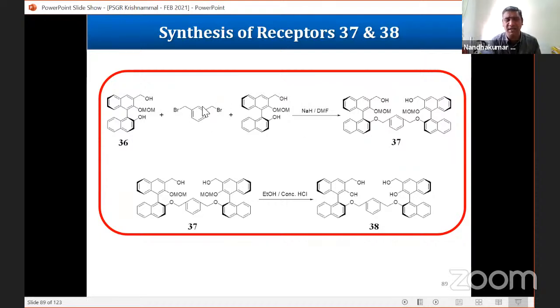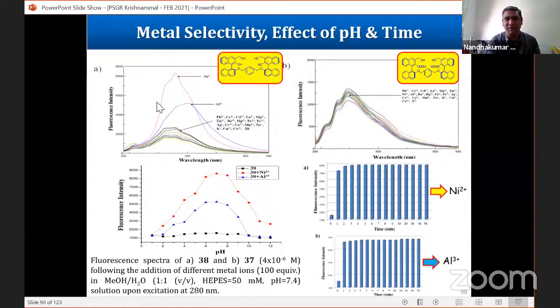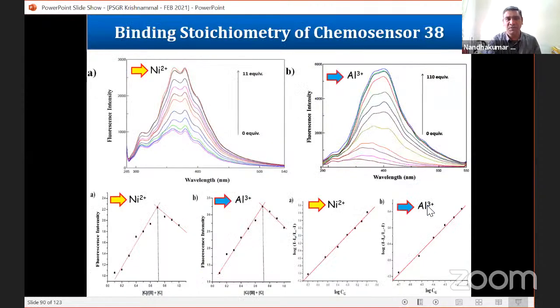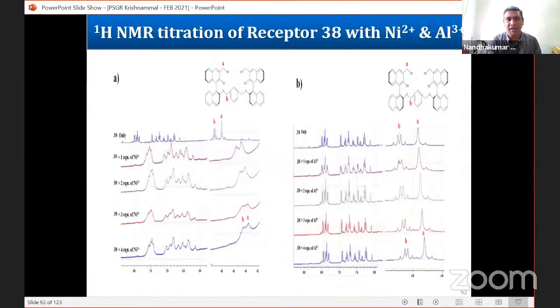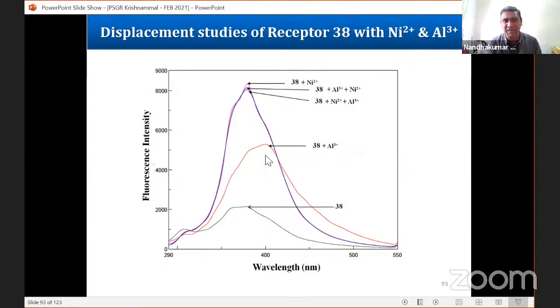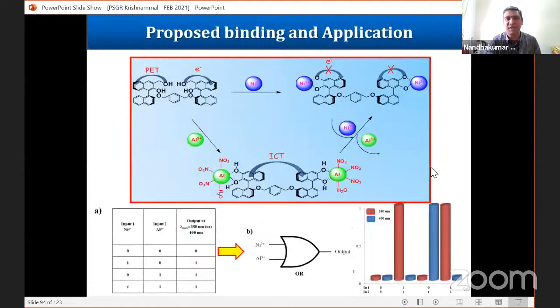We are using the same xylene dibromide, and with our binol we have done this. So you can see here it selects aluminum as well as nickel. Nickel gives enhancement, while for aluminum there is a shift, so an internal charge transfer takes place, but for nickel there is a blockage of photo-induced electron transfer. PET is blocked and you get chelation-enhanced fluorescence with the help of nickel, and the other is for shifting. The rest are the same: the kinetics and NMR spectra, and this is the displacement. First it detects aluminum, and then when you add nickel, aluminum is displaced.